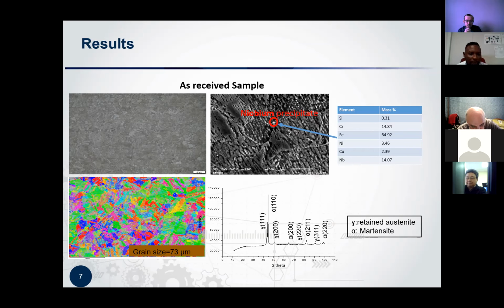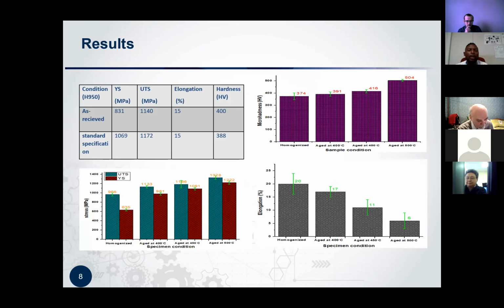Furthermore, with the help of EBSD, we did measure the grain size, which was 73 microns. And we also did XRD, which confirmed the phases present. We had retained austenite, as expected, and then we also had martensite.